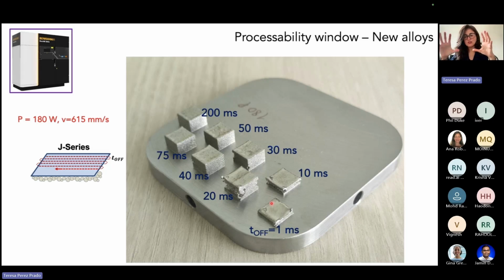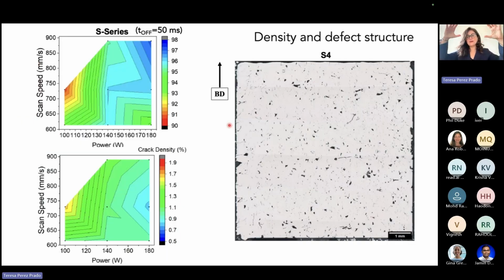So almost within this orange window of processing parameters, irrespective of the position, I'm showing you here just one set of processing conditions, 180 watts, 615 millimeters per second. And you see how the cubes look when we print them with different time delays. So even for these excellent alloys with high glass formability, we still need time delays if we want to retain the shape within that domain. So we fixed a time delay of 50 milliseconds. And then we thought, let us now fix this time and expand in terms of scan speed and laser power. Let's explore. The first good news there was that we did get a little bit higher density.